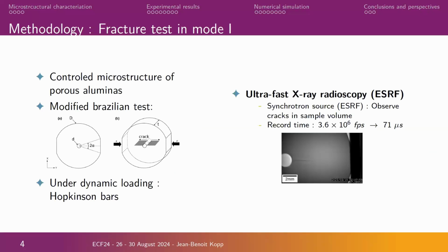So the methodology is, first of all, to control the microstructure of porous alumina. We will talk about that just after, with the manufacturing process of the material. We use a specific specimen geometry, which is a modified Brazilian test. I will talk about that later because we know this kind of specimen geometry well in the lab. The interesting thing is that with this geometry it is possible to apply dynamic loading with a split Hopkinson bar. And finally, we were lucky to use ultra-fast X-ray radioscopy at the ESRF, and it was possible to follow the fragmentation with information about the microstructure, even if it's only radioscopy in dynamic, because tomography is not possible with this kind of fracture time, but it was possible to have radioscopy.